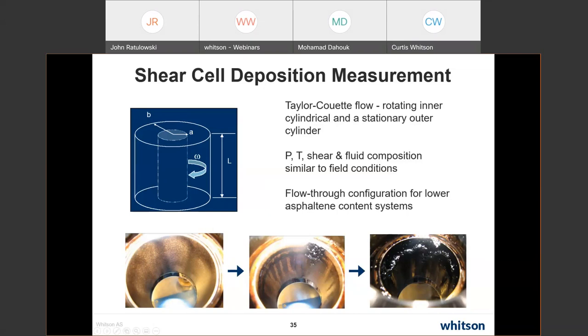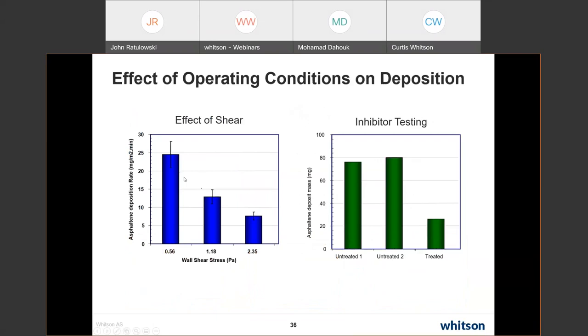All right, so the idea on doing this was to look at the effect of shear, and this is something that's really important in asphaltene deposition. You won't see a lot of asphaltene deposition at very high shear rates. These deposits are not always that competent, so it depends on the asphaltene, but often at very high shear rates, you won't have a problem, and you start getting a problem as you drop down to lower shear rates. And this just shows some inhibitor testing, and in this case, the inhibitor that we tested was effective, but kind of like wax, it doesn't completely eliminate the deposit, but it reduces it quite substantially.